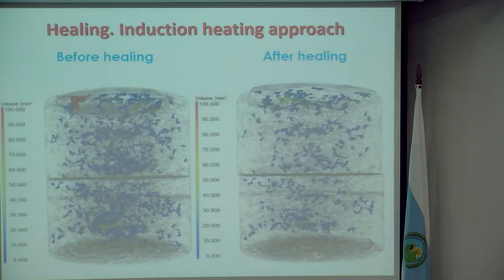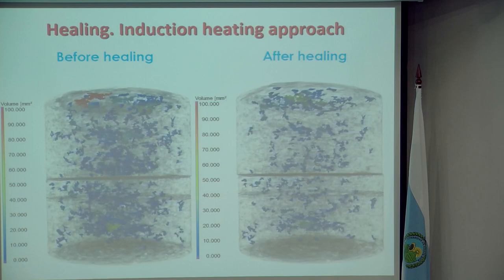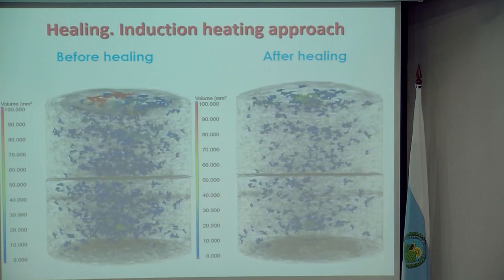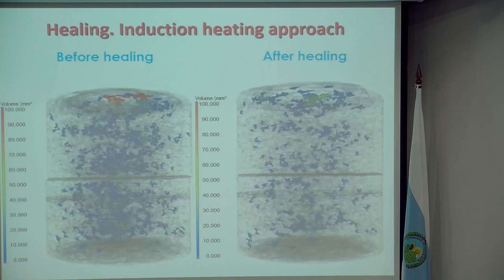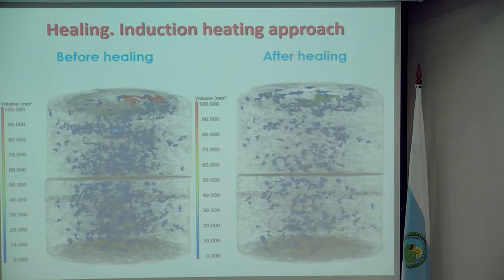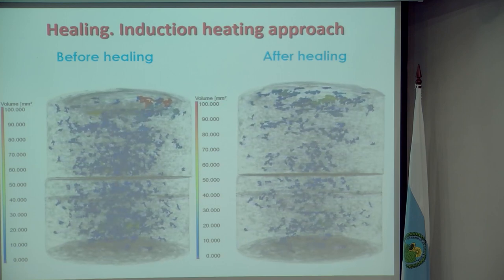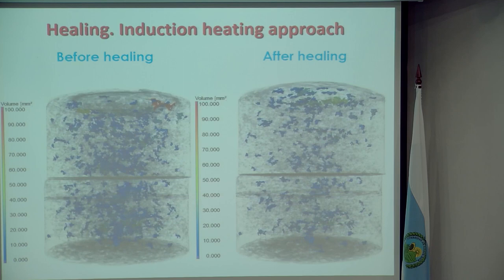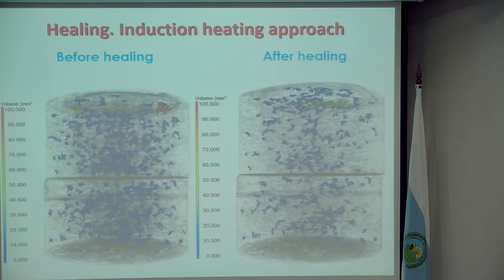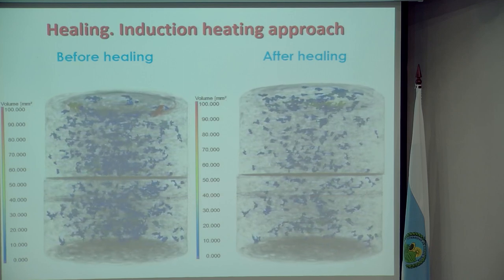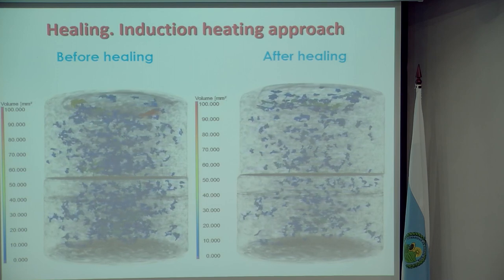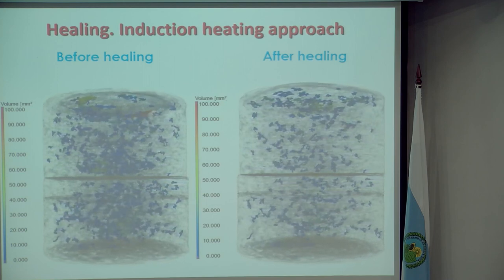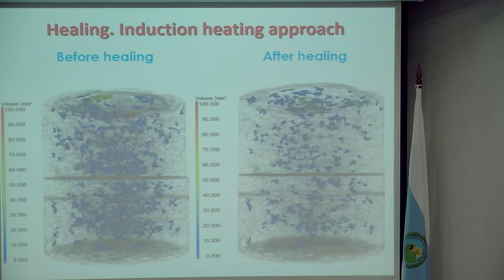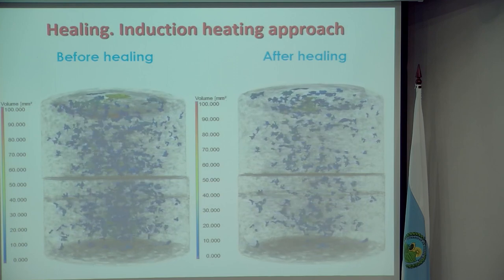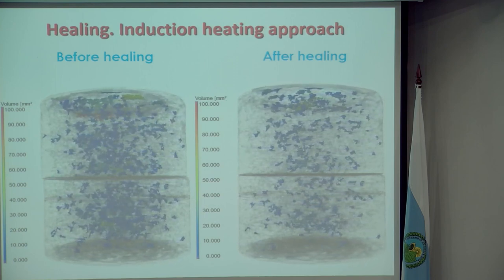And if we look at individual particles, so these were specimens that were put under the X-ray CT scanner, looking at their void content, which was effectively in terms of damage. So these were not fracture tests. This was basically just damaging these specimens through some kind of completed or repetitive load, and then looking at the change once within the induction heating in terms of the void content. And there are significant differences. There is significant healing taking place.